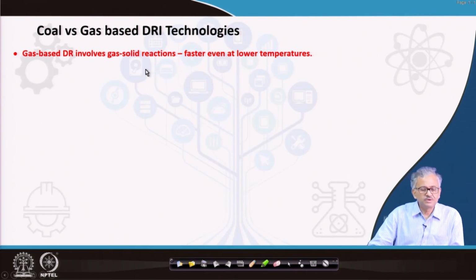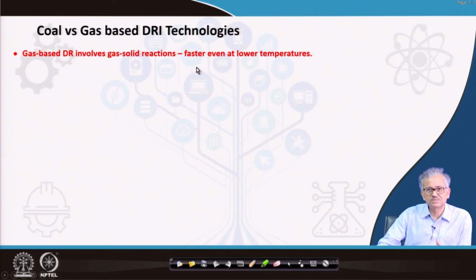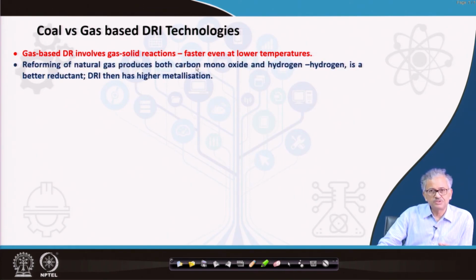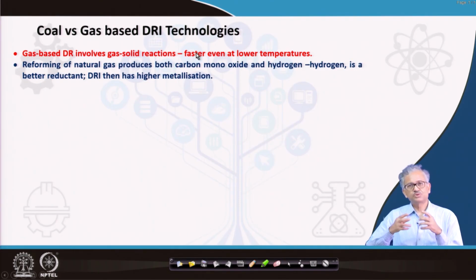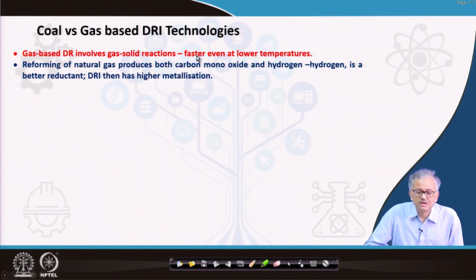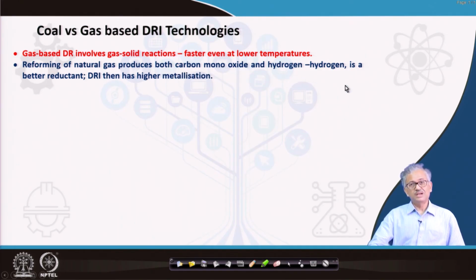Now, some differences between coal and gas based DR technology. Gas based DR involves gas solid reaction, which is faster even at low temperature, because gas solid reaction is much faster compared to solid solid reaction. The coal based process also involves gas solid reaction, but here it is basically a counter current process. The gas is moving from the bottom and the solid is coming down, so the gas solid interaction is much greater in the gas based process. That is why the gas based process can be carried out with higher kinetics at comparatively lower temperature.